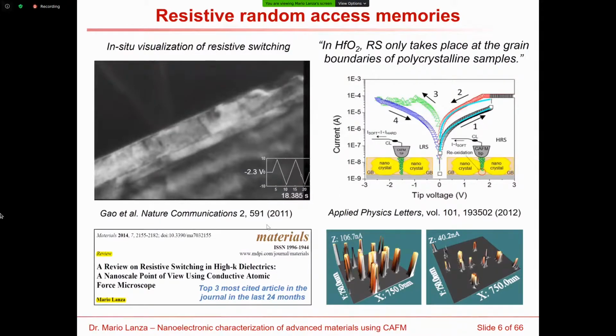So using this technique, I have analyzed the resistive switching in many different materials. Here you see one example. We were the first team in the world who demonstrated that the resistive switching in polycrystalline high-K dielectrics was produced only at the grain boundaries. And this was possible because the conductive AFM has a very high lateral resolution. So it's a very great advantage compared to traditional studies that use the probe station, for example.